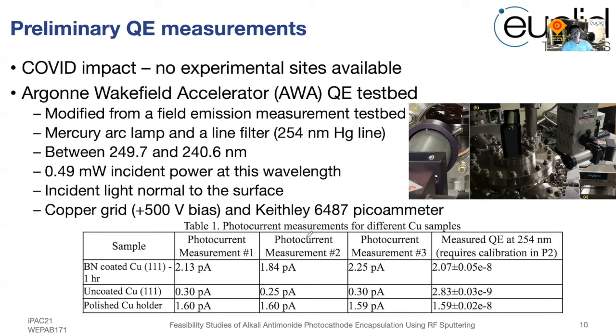The incident light is normal to the surface, and we use a copper grid, which has a plus 500 volt bias, and a picoammeter to measure the photocurrent. So we compared a few samples, which included the boron nitride coated copper 111, the uncoated copper 111, and a polished copper holder, which is already there in the system. As you can see from the comparison, the photocurrent from the boron nitride coated copper 111 was greatly enhanced from the uncoated copper 111, which was predicted from the DFT simulations.